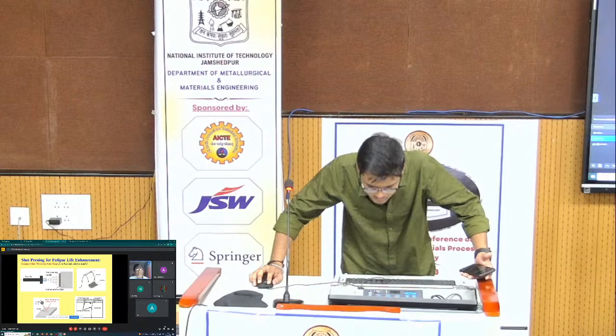Exactly in the same analogous manner, if I want to give more and more deformation beyond yield strength, it will only result in plastic deformation. So which is why we first of all increase the yield strength of that surface through carburizing or carbonitriding, and then if you start shot peening, you can lock up more stress. This is an interesting point.